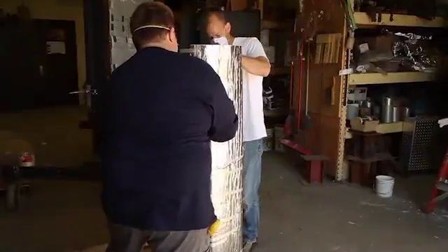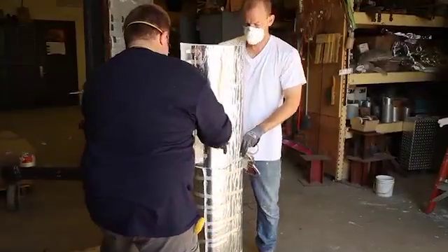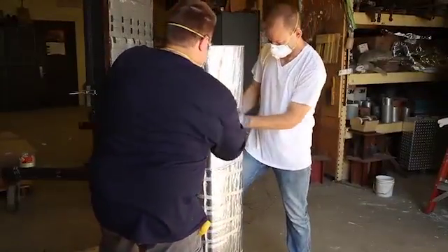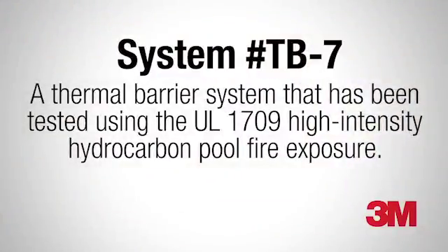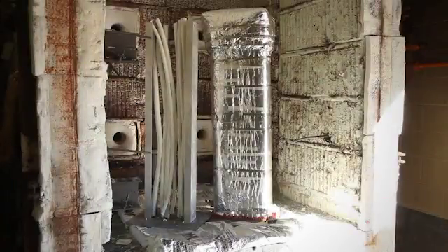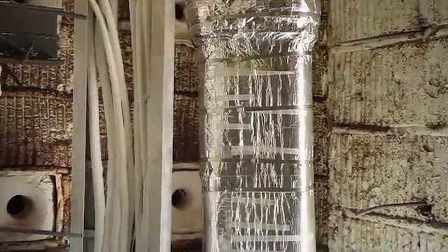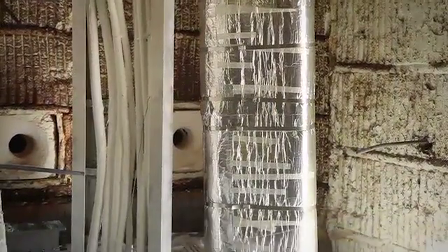In this instance, 2 layers were applied in accordance with system number TB7, which is a thermal barrier system that has been tested using the UL 1709 high-intensity hydrocarbon pool fire exposure that's commonly required in the oil and gas industry. Once the protective materials were applied, the cable trays were loaded into the test furnace and exposed to the high-intensity hydrocarbon pool fire temperatures.